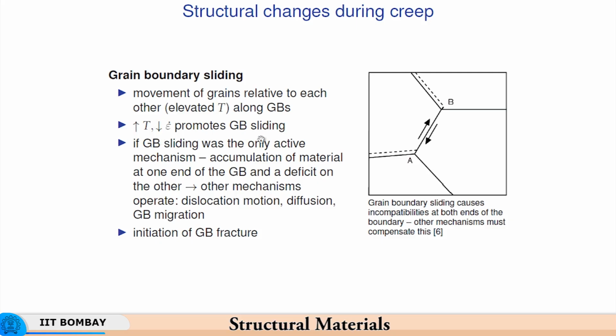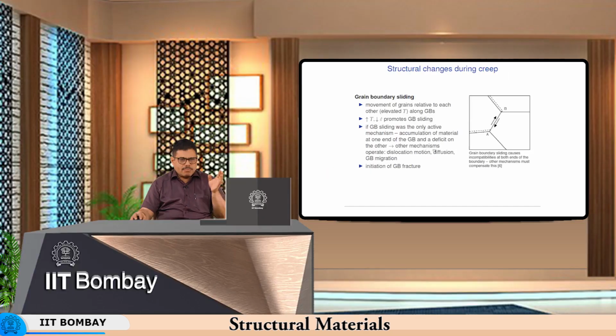So, grain boundary sliding is the active mechanism, and so as the temperature is large, strain rate is low, then you have grain boundary sliding as a predominant mechanism, and that perfectly fits in with the fact that when you have diffusion, which is a slow process, you need a sufficient amount of time and sufficiently large temperature. So, we have these two things possible when you have high temperature and a lower strain rate, because you have more time available under these conditions. And then this grain boundary migration or the diffusion results in balancing of the material. For example, you do not have accumulation of material at one end and deficit on the other. So, these compensatory mechanisms continue to operate and balance the two.